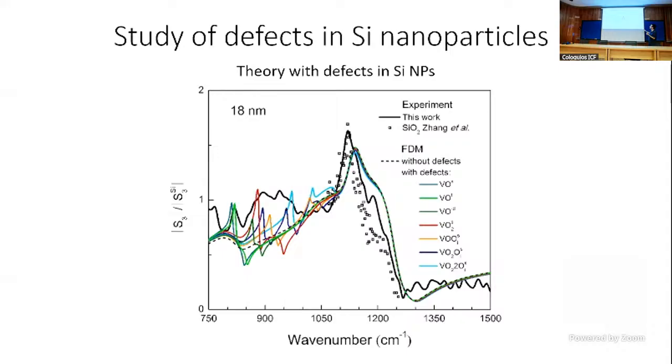This is chemistry again. There are many different combinations, all of them vacancies and oxygen, with 1, 2 or 3 atoms combined, so each one of these defects will show up in a different position here. Combined, they will give you a peak in this region here.